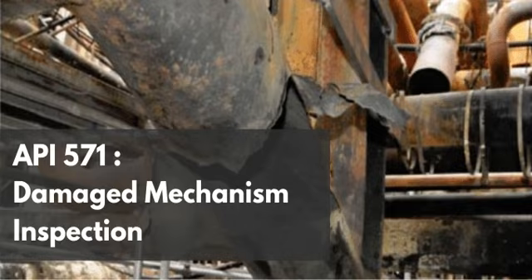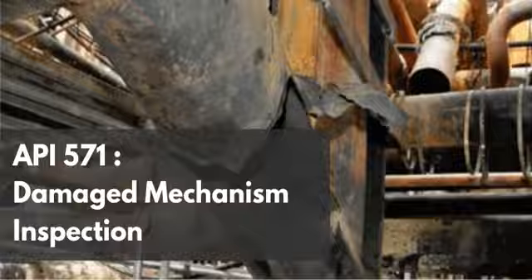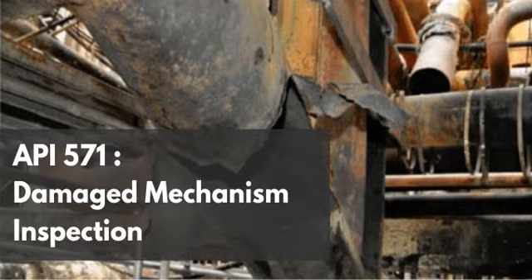So that differential thermal expansion between the thin nozzle and the thick shell creates immense localized bending stresses at the weld junction. It does. So at the bore of that nozzle, you have triaxial stress concentrations, magnified hoop stress, longitudinal stress, and massive thermal gradients. And cracks will always propagate perpendicular to the maximum principal stress, right? Always. Because the hoop stress attempting to pull the bore open is so high, the cracks initiate at the edge of the hole and propagate outward into the shell plate.